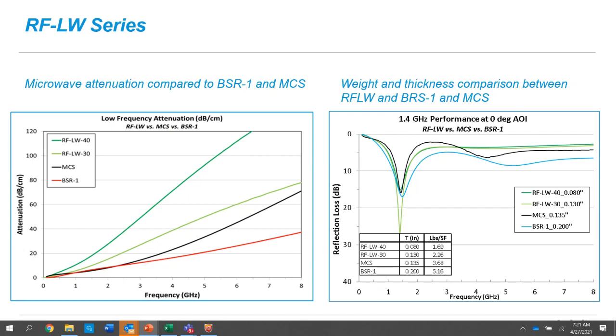BSR1 and MCS, that's the black and red curve. This is attenuation, which is calculated from the permeability and permittivity of a material. So how much energy is attenuated as it goes through. And you can see that versus frequency. Certainly as wavelengths get shorter at higher frequencies, attenuation increases. But now if you look at the LW30 and 40, and that's 30 and 40 volume percent loading, what you can see is a much higher attenuation level.